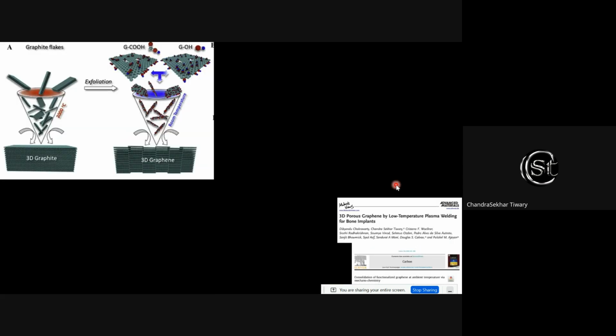Now, graphene can also replace graphite in a few applications. For example, the graphite industry takes a maximum amount of energy in processing the graphite blocks. So you take graphite powder, put it together, and in order to sinter it, you need a temperature of more than 1500 or 1600. And then you sinter the graphite, which can then be utilized. Now, the high temperature sintering is one of the major energy consuming components in the processing of graphite. Now, the question is, can we take graphene, put it together, and achieve certain properties which are comparable to graphite?